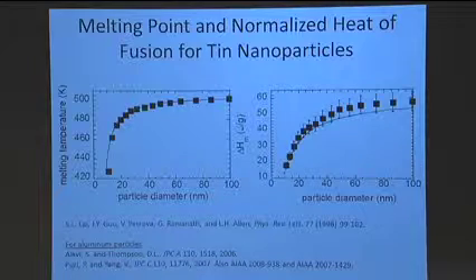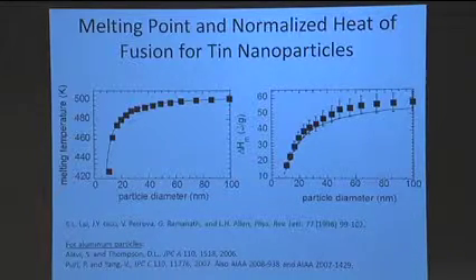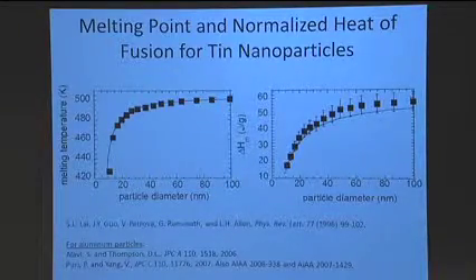If I look at the heat of fusion, the energetics for this to occur, you can see the same sort of trend in terms of the energetics falling off. Now, obviously, these are from experiments. There have been a lot of molecular dynamics calculations done. I put a couple here. Don Thompson and Vigor Yang have looked at aluminum particles, doing some MD simulations.